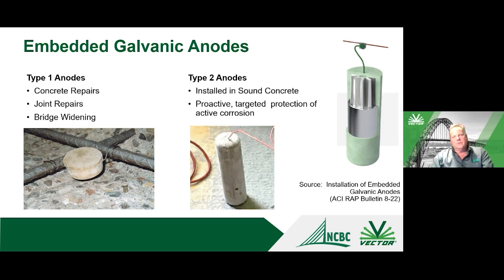So we start looking at what can we do to provide additional protection. One method is to look at what we call type 1 anodes. These are galvanic anodes that are tied directly to the steel. There's also type 2 anodes, which I'll show you some examples of, which can be installed into holes that are drilled in sound concrete. And then there's even a third type of anode that's a kind of a newer system that's a combination of embedded impressed current and galvanic anode.